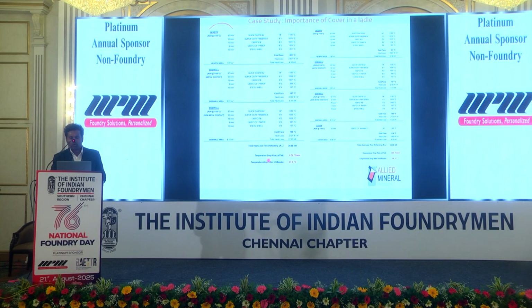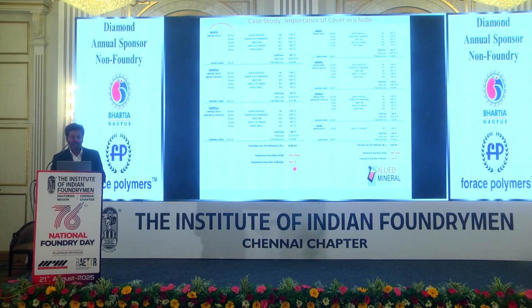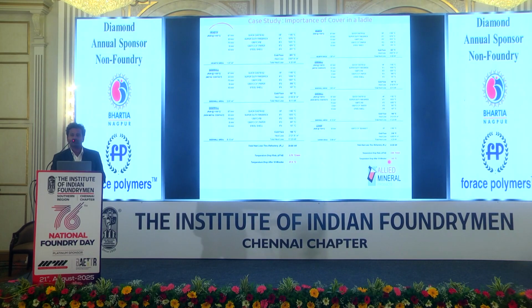So if you see the heat loss, the temperature drop rate is like 5.79 Celsius per minute. For 10 minutes, the loss is like 57.9. By just introducing a ceramic blanket, we can reduce the temperature loss by more than 80%.